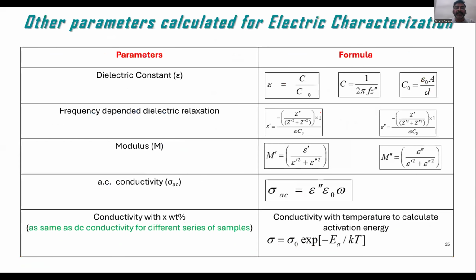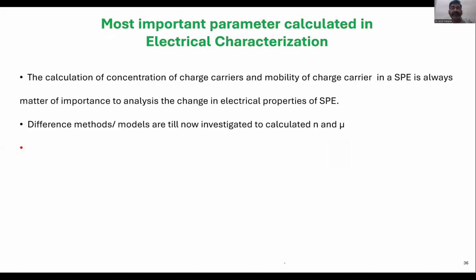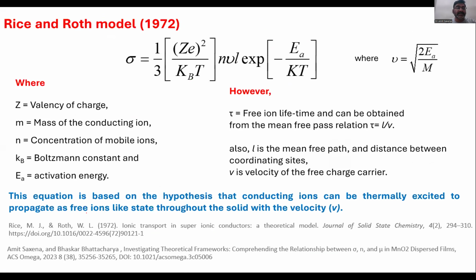These are some other parameters which we can study out of the values obtained from the impedance spectroscopy characterization: the dielectric constant, capacitance, epsilon prime, epsilon double prime, you can say the real and imaginary parts, modulus, AC conductivity, and more interestingly, we can have the concentration and mobility based system. I will introduce the three different theoretical models which can be used to analyze how the concentration and mobility behave.